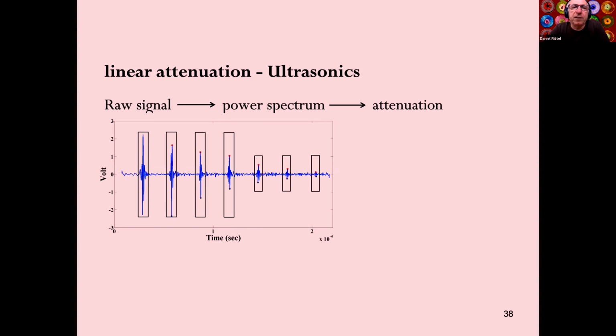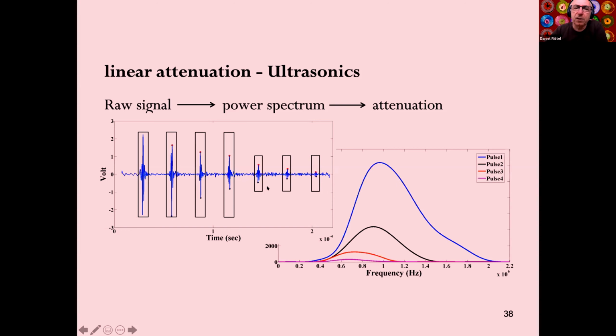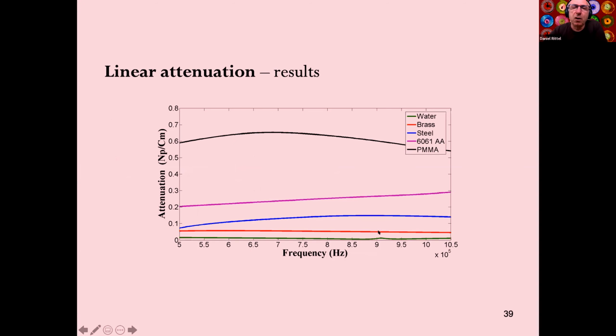What I call linear attenuation, ultrasonics. You apply very, very weak signals, as was alluded to in a talk that I listened to yesterday, and you simply analyze the various reflected pulses and calculate the attenuation. That's your attenuation as a function of frequency, and that's the result. First of all, you do that with water, brass, steel, PMMA as a function of frequency. The frequencies are relatively high, of the order of 10 to the 5, 10 to the 6. And this is the attenuation as a function of frequency.